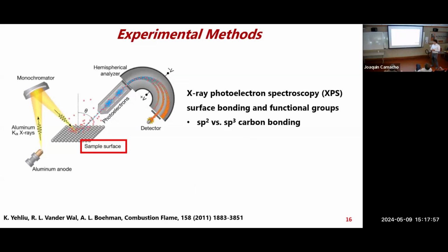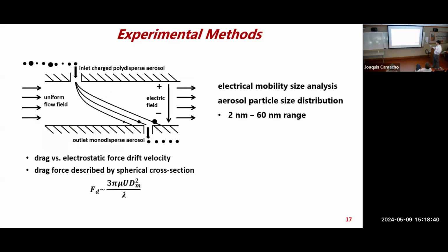Another very useful technique is X-ray photoelectron spectroscopy. It also focuses on the surface. By shooting photons at the surface, you can keep track of the energy you're putting in, and then it'll shoot off an electron, and that will give you the binding energy. In terms of soot, we use that to determine the amount of sp2 bonds versus sp3 bonds, like double bonds for graphite versus sp3, diamond-like or amorphous. So this XPS measurement gives you an idea of sp2 carbon bonding versus sp3 carbon bonding, which is very useful for studying crystalline structures.